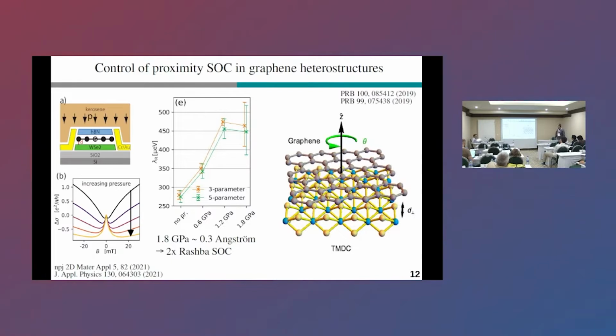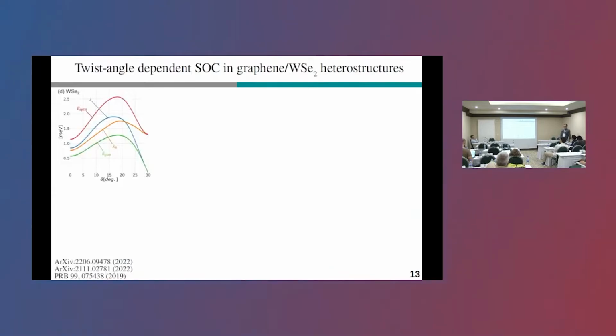And now the second thing that can be done is, of course, twisting. Recent tight-binding calculations have shown the following. When you place graphene on tungsten diselenide, the valley-Zeeman spin-orbit coupling in graphene will follow this blue line. So we have this intermediate maximum at around 15 to 20 degrees of the twist angle, and it then goes to 0 at 30 degrees, which is due to symmetry.